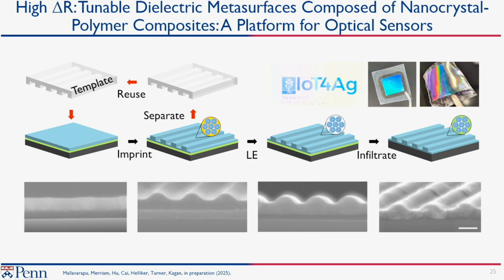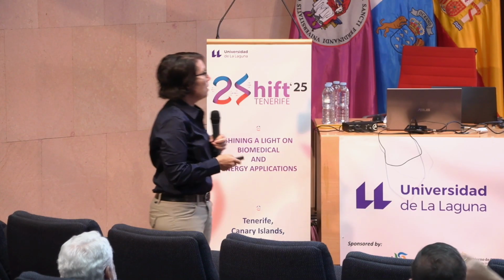And then if we heat this, you can get what's known as capillary infiltration. If you go above the glass transition temperature, the chitosan will then diffuse into the pores of the structure, and now you get this mixed system here. And we're just following it. Here, this is just a blank layer of chitosan and titania. Then we imprint into the titania. Then we do the ligand exchange. That's here. The chitosan's still here. And after we anneal it, you can see the chitosan layer underneath is almost gone. It's all basically infused. And you can study that both chemically and spectroscopically to show that that's the case.